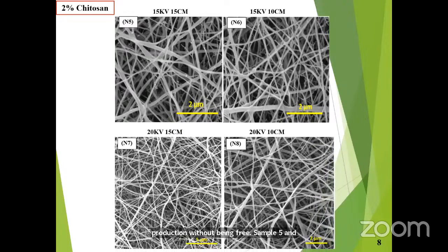Samples 5 and 6 were produced at 15 kV voltage while keeping the working distance at 15 centimeter and 10 centimeter, while samples N7 and N8 were produced at 20 kV voltage while keeping the working distance at 15 centimeter and 10 centimeter respectively. And here we also see that smooth nanofibers were produced with the 2% chitosan solution concentration.